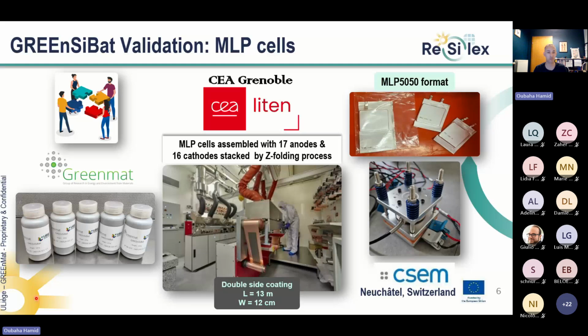The electrochemical properties of our composite, as I said, were evaluated thanks to our collaboration with CEA, where they produced electrodes at industrially relevant conditions. You can see that they can produce double-sided coating using our silicon in their facilities with a length of up to 13 meters and a width of 12 centimeters. So we are close to actual industrial production. And there they assembled a multi-layer pouch cell of 50 by 50 format, and the electrochemical properties were evaluated in both CEA and CSEM to validate the composite.